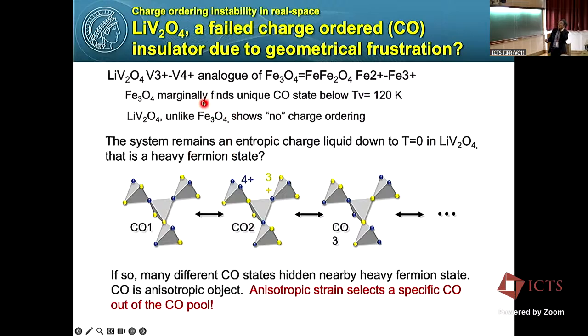Now, lithium vanadate is a 3+/4+ analog of magnetite. But magnetite eventually finds a unique charge order state, Verwey order, below 120 K. But lithium vanadate, unlike magnetite, shows no charge order. So our working hypothesis is that the system remains an entropic charge liquid with macroscopic degeneracy of different charge order states, which is the heavy Fermion state. And if so, many different charge order states are nearby the heavy Fermion state.